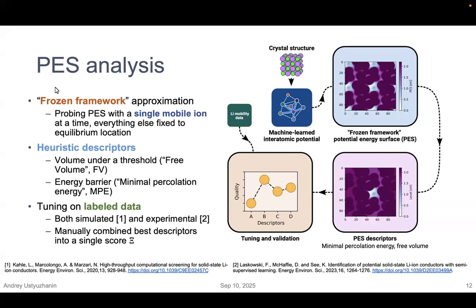So to make it more natural for machine to see, we designed so-called descriptors that characterize how these volumes of low potential, how nicely these connected with each other. And so there are basically two kinds of descriptors, like a free volume. So it's a volume with energy below a threshold, or energy barrier. So it is minimum percolation energy from position of atom inside one lattice and the same position in adjacent lattice. So like how much energy you need to add to get from one position to another.